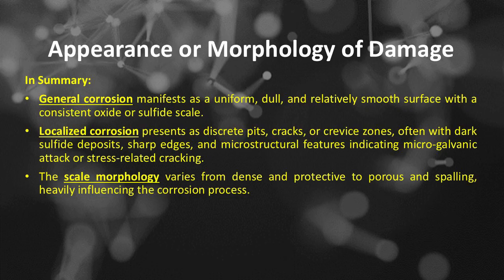In summary of the appearance and morphology of high-temperature hydrogen or H2 and hydrogen sulfide or H₂S corrosion, general corrosion manifests as a uniform, dull, and relatively smooth surface with a consistent oxide or sulfide scale. Localized corrosion presents as discrete pits, cracks, or crevice zones, often with dark sulfide deposits, sharp edges, and microstructural features indicating microgalvanic attack or stress-related cracking. The scale morphology varies from dense and protective to porous and spalling, heavily influencing the corrosion process.